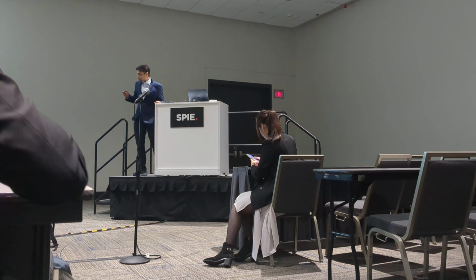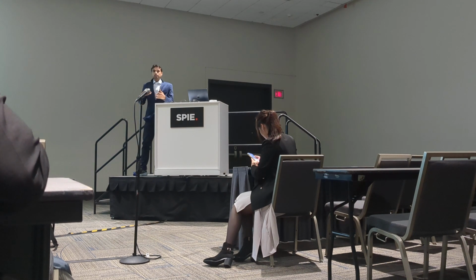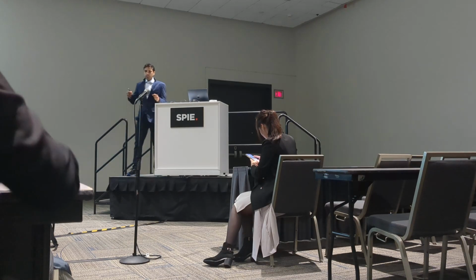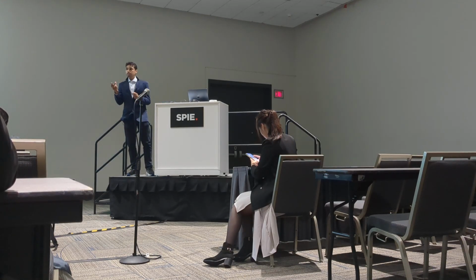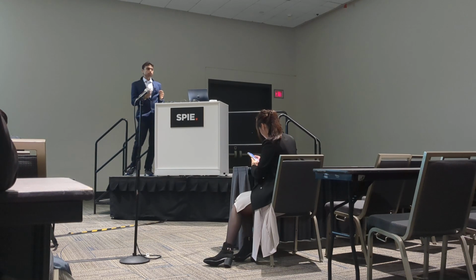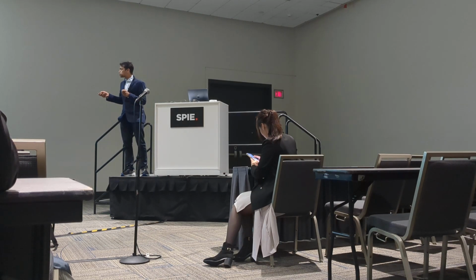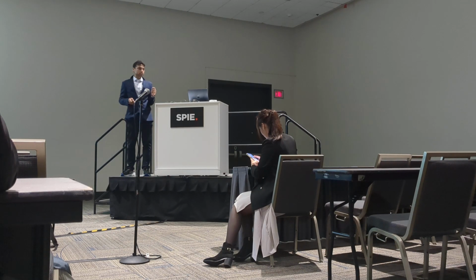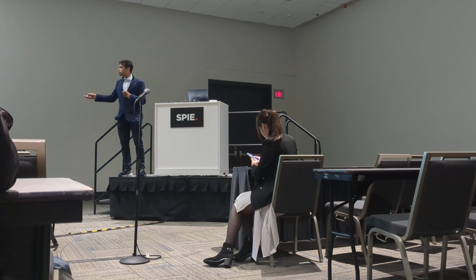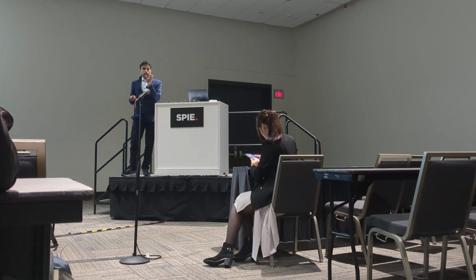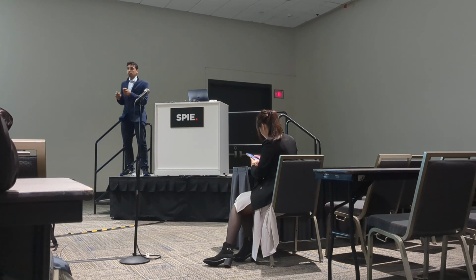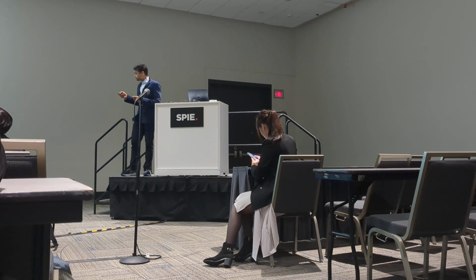So, how do we fabricate our structure? It is a simple step. We take a substrate, and because we are interested in a mechanically deformable material, we use a polymer. In fact, it is an elastomer called PDMS, polydimethylsiloxane. The way it is made is we take a particular fraction of the PDMS base and mix it with a cross-linking agent. The fraction of that cross-linking agent determines the extent of cross-linking in that material.